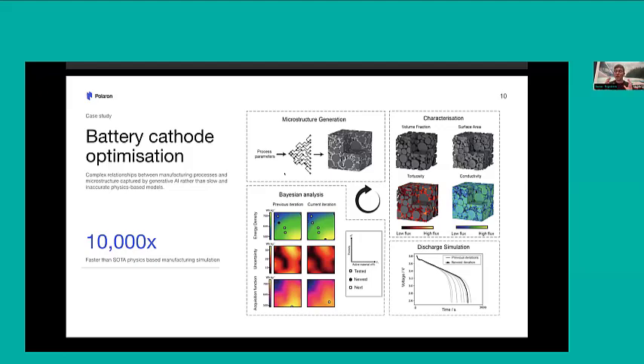So we take image data collected under different process parameters. So in this case, we varied the mixing and the calendaring process. So we take some images under varying mixing and calendaring, and we train a model that then can predict how the structure will change as we change those parameters.